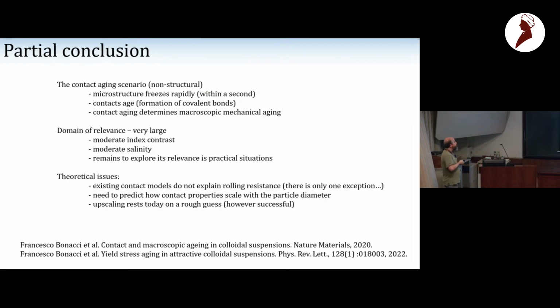So the partial conclusion is we identified a contact aging scenario where the microstructure freezes, contact age, and contact aging determines the macroscopic response. We expect this scenario to have a very large domain of relevance. Most suspensions in nature have index contrast, so they have strong van der Waals adhesion. They are often ionic, even for moderate ionic strength. In the labs, many people have been working on model glasses, and for that you want systems which are not getting in solid-solid contact. But in nature, many suspensions will be adhesive.